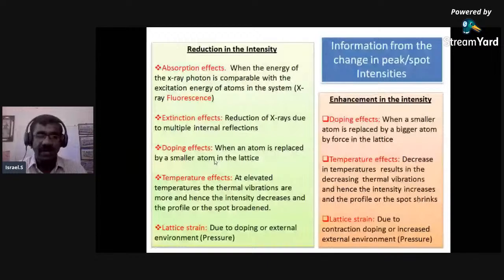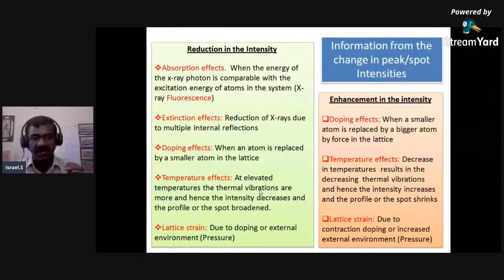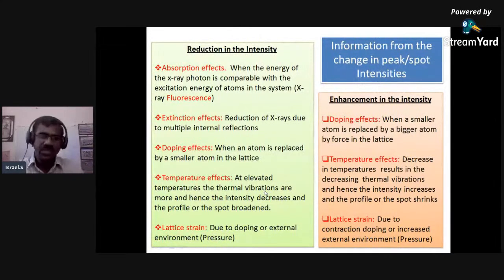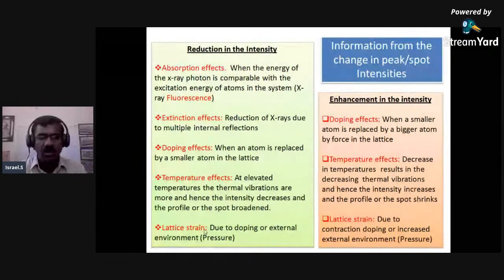So you can check whether the doping has been done into the system by looking at the reduction in intensity. Temperature effect: suppose you are treating the crystals at elevated temperature or at lower temperatures, then because of the vibrations of the atoms, you get diffuse scattering, which we call the TDS effect. Because of this diffusion in intensity, there will be a reduction in intensity. As I talked about, because of the environment also, due to external pressure, in pressure dependent XRD, or due to doping, you can find out the lattice strain. Similarly, the enhancement of intensity.